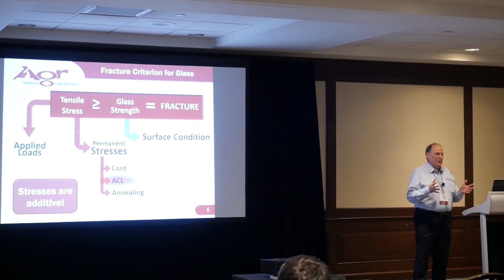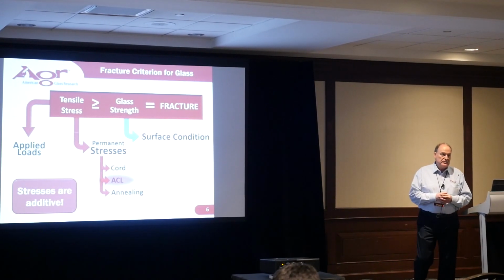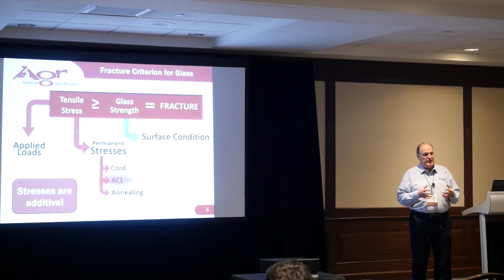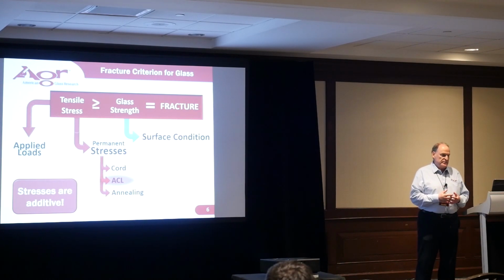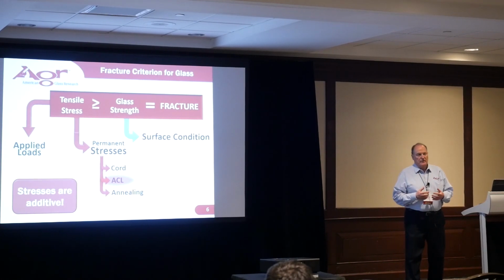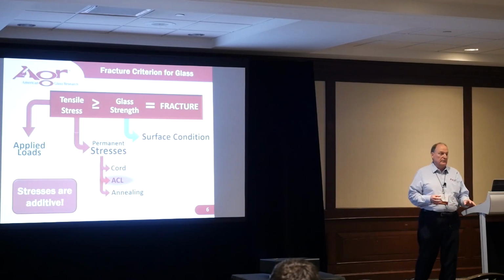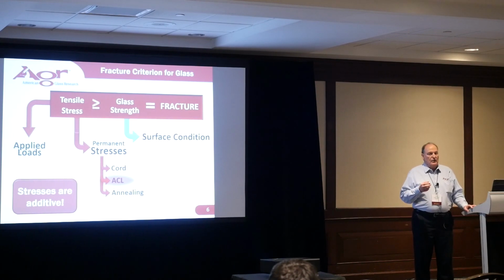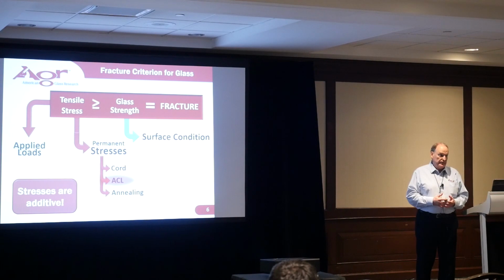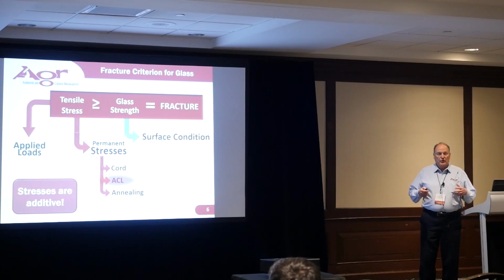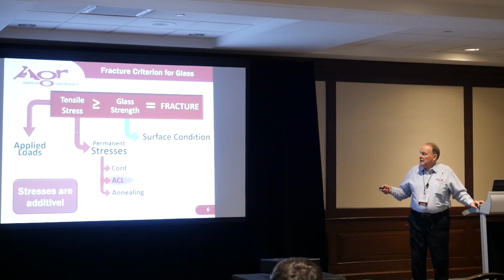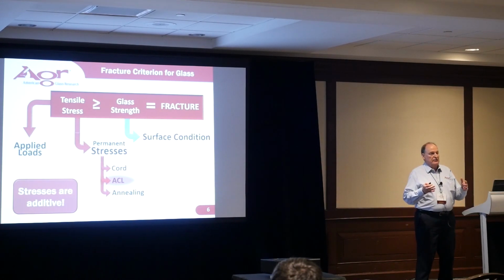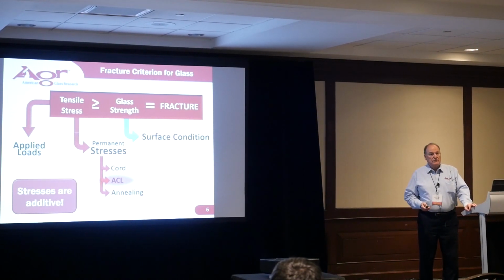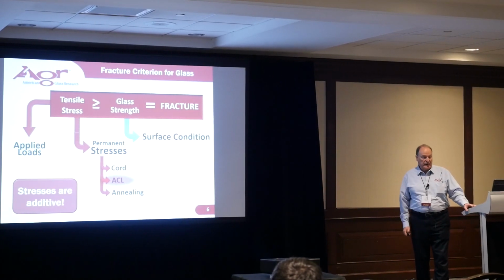Now, the purpose of performing design evaluations of glass containers is to make sure that the stresses that are generated by these applied loads are always lower than the expected surface strengths. There have been many, many studies conducted. We know what the expected minimum strength is for a refillable bottle, even after it's been abused for years and years and years. We also likewise know what the minimum expected strength of a non-refillable bottle is after one passage through a filling line. So this surface strength value is relatively known under normal, expected, typical conditions. It then is possible to design the bottle so that it has the proper features, proper thickness, so that under expected loads, those tensile stresses will be lower than the strength and the bottle will be viable. And that usually happens. It's the rare occasion that bottles break.